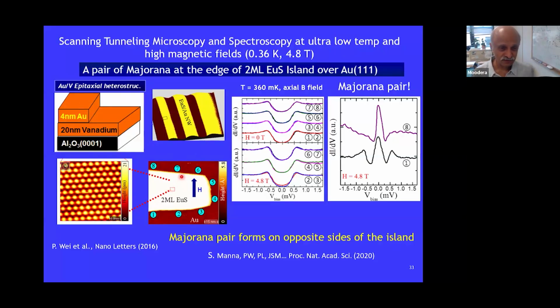Then you have the europium sulfide sitting on that. It turns out that if you spectroscopically scan the whole edge of this europium sulfide island, you find that at the location of 1 and 8, in the presence of a large magnetic field, you can see the signature of these Majorana modes, these two modes.